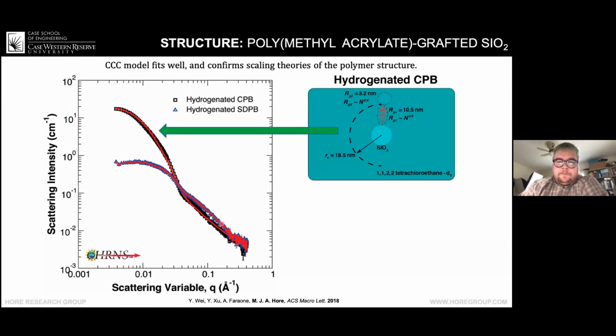So what we found here for the sample that had the hydrogenated CPB is what I'm showing schematically here. The reason that I chose these colors that are hard to discern is because this is what the neutrons are seeing when they scatter from the particle. The scattering length of the silica core and the solvent are almost the same, so there's very low contrast between these two. Similarly, the contrast between the deuterated outer block and the solvent is very low, and it's almost the same as silica. So these don't have a lot of scattering length density difference, whereas the hydrogenated chain does.